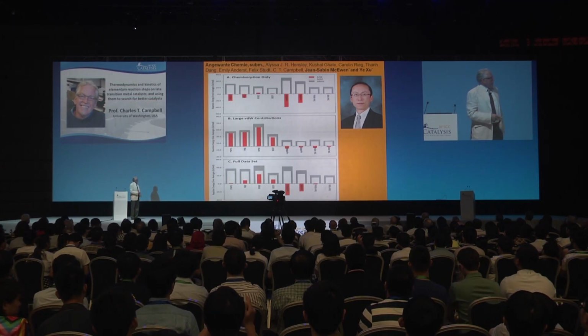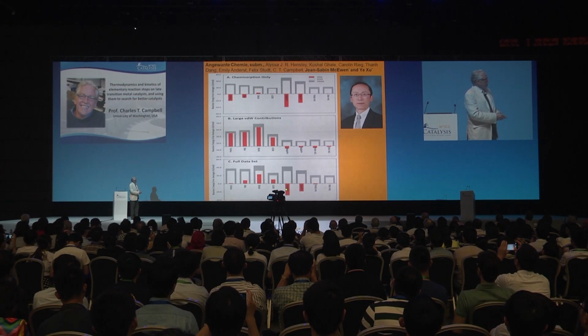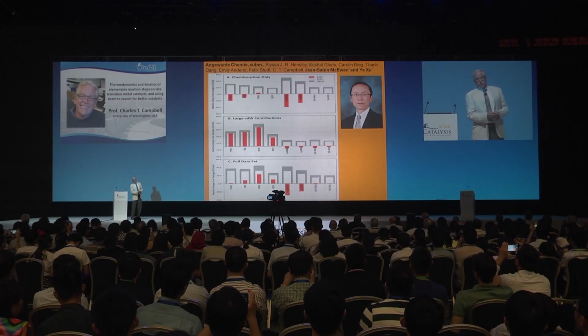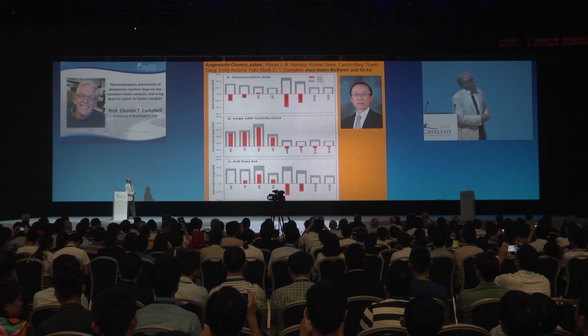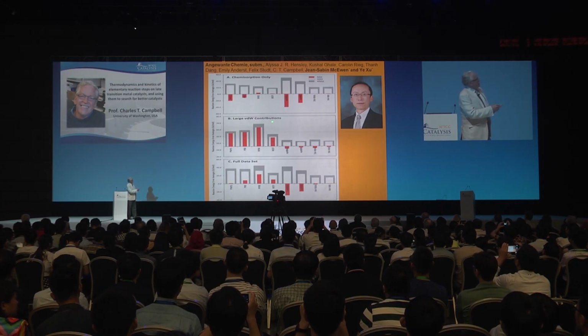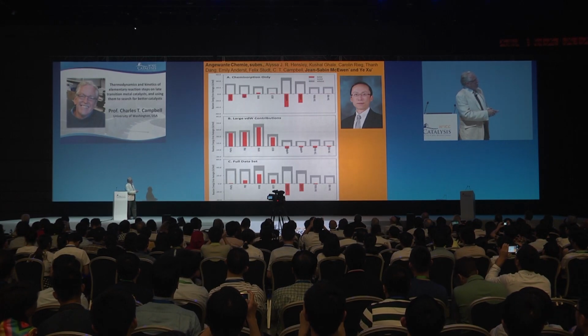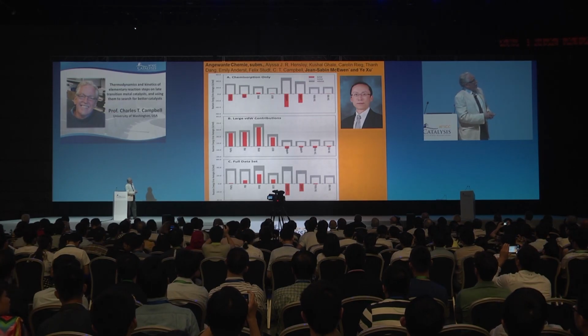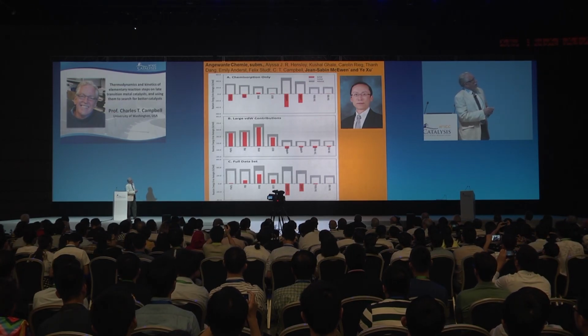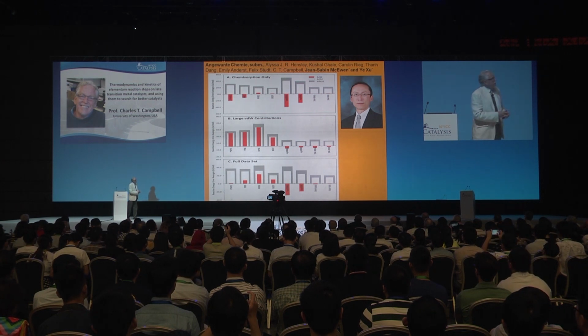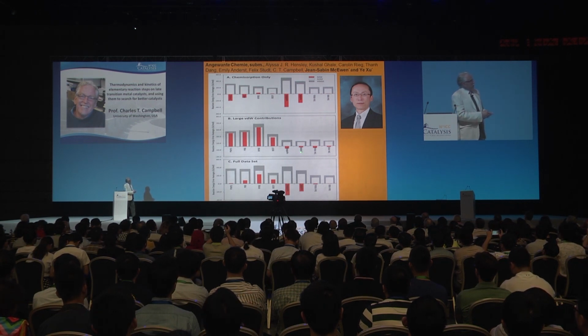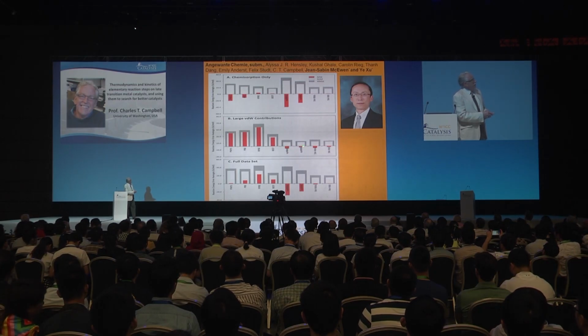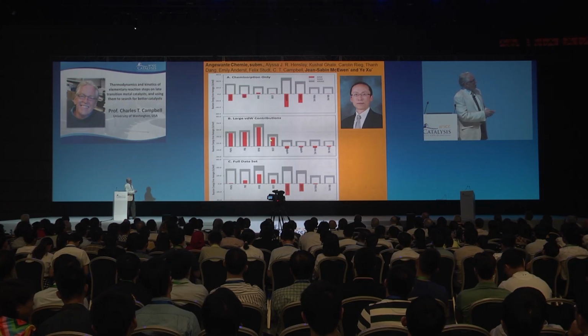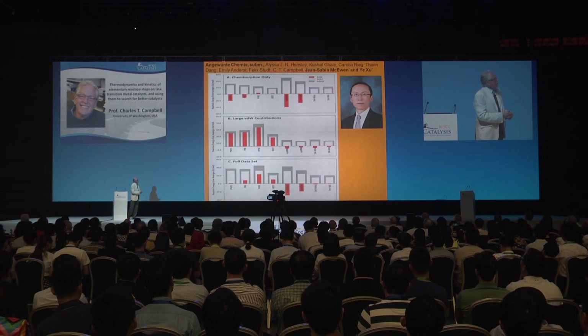When we published that, I was thinking that Angelos Michailidis' optB86b-vdW or optB88-vdW methods might give better results for those kinds of molecules with large van der Waals contributions. And so together with Yi Zhu and Jean-Sabine McEwen, who are young chemical engineering professors, we compared our experimental measurements table to the results from these. And in fact, they do quite a lot better for these, but they do much worse for the small adsorbates that are strong chemisorption species.